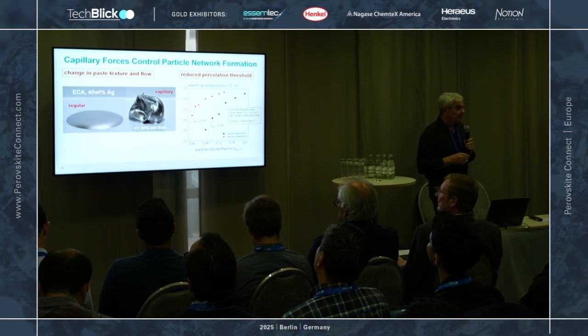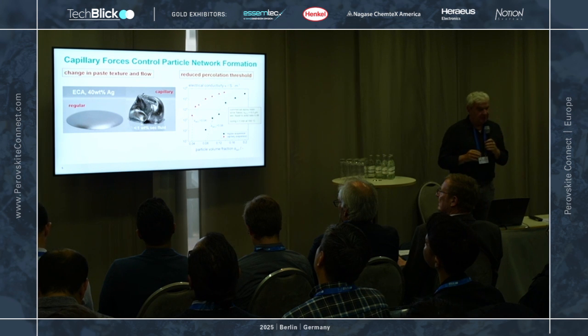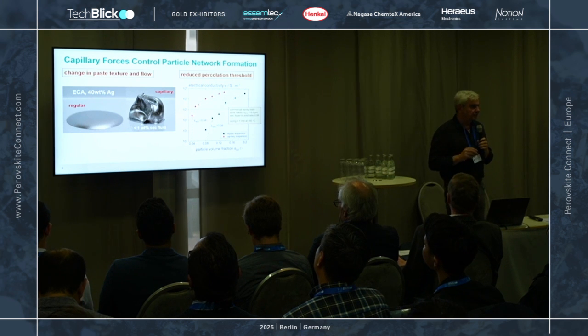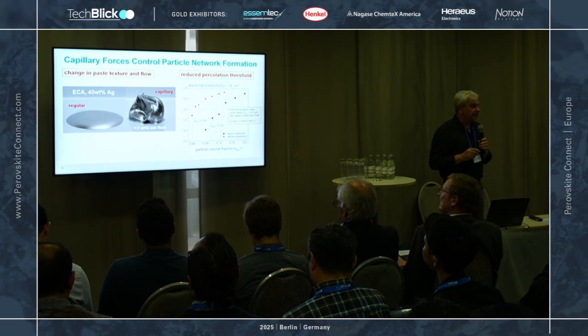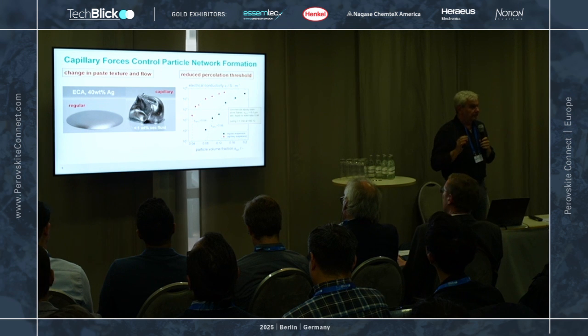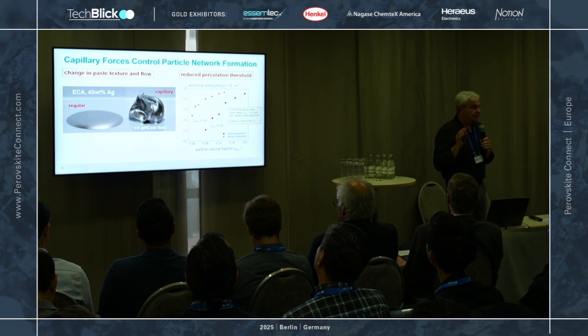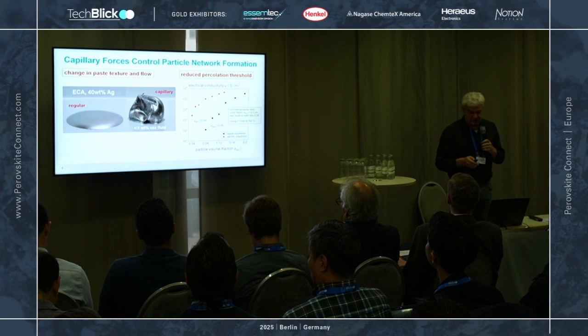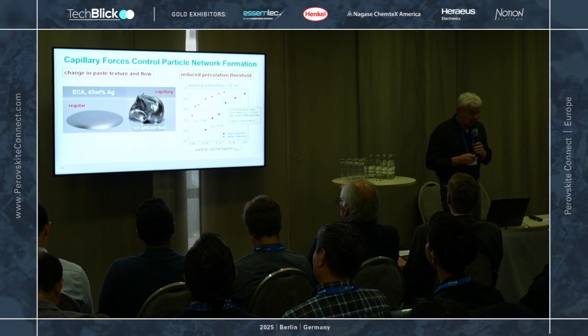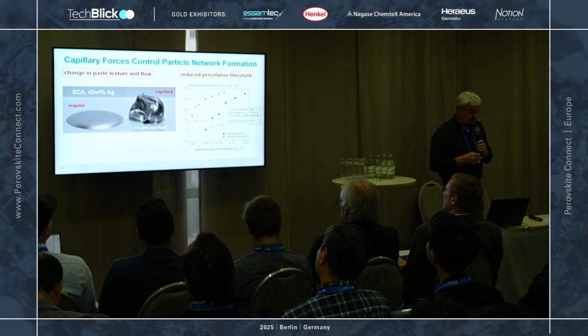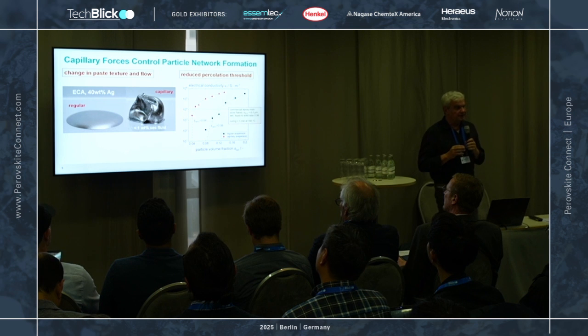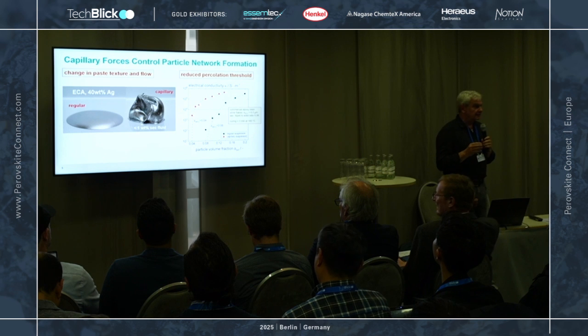But if you add a trace amount of a secondary fluid, you change the texture completely. And what happens due to the network formation is that the percolation threshold in the system is shifted drastically. You see that in the graph on the right-hand side, where the electrical conductivity is plotted as a function of particle volume fraction. You see that this strong increase in conductivity